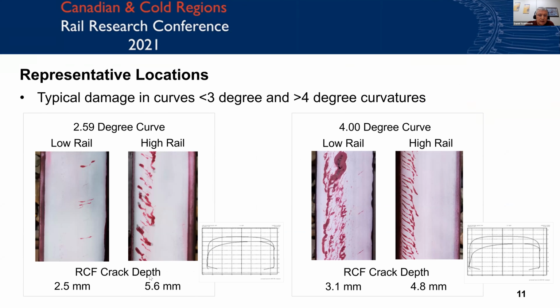So here you see that high rail that has a crack of 5.6 millimeters. The low rail has some damage, but not nearly as extensive as the high rail, because the super elevation is positive, and the high rail suffers in this case.